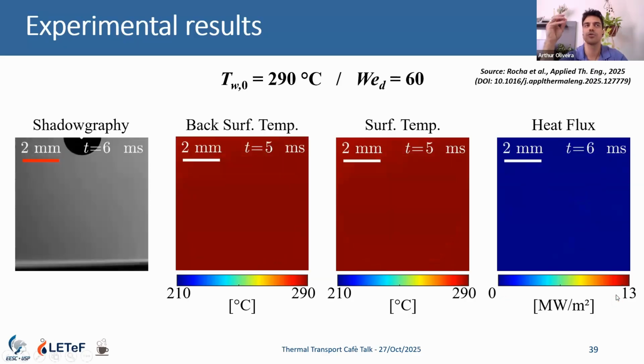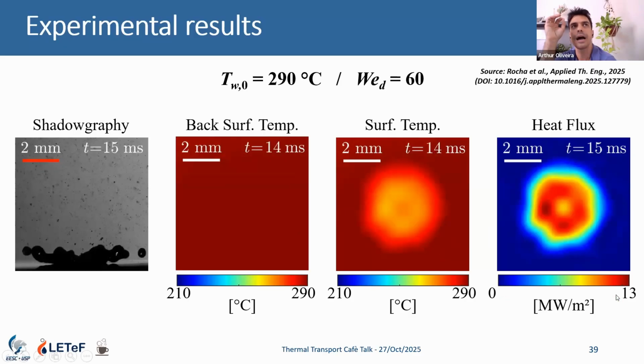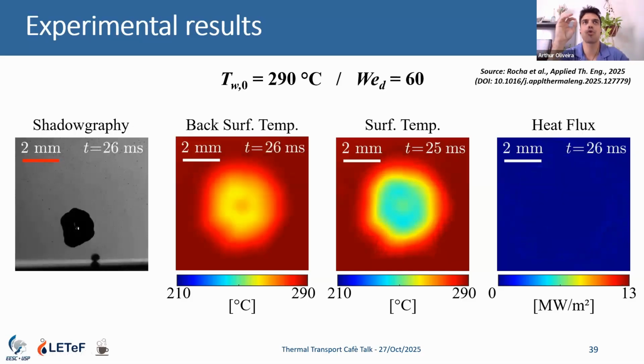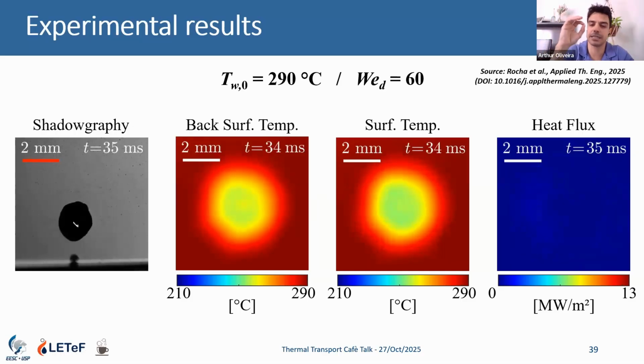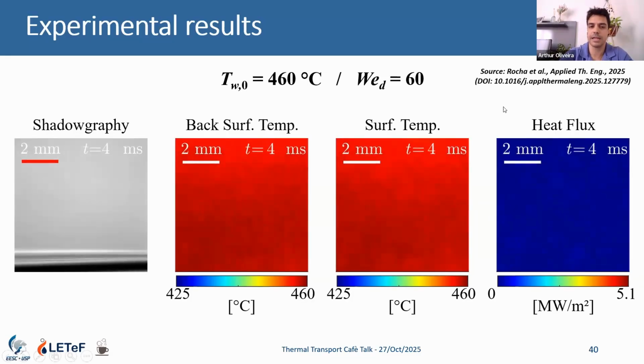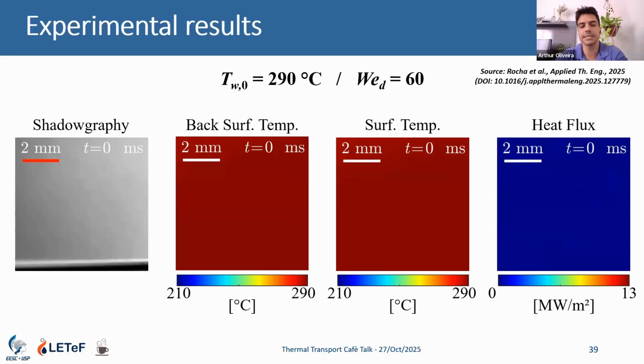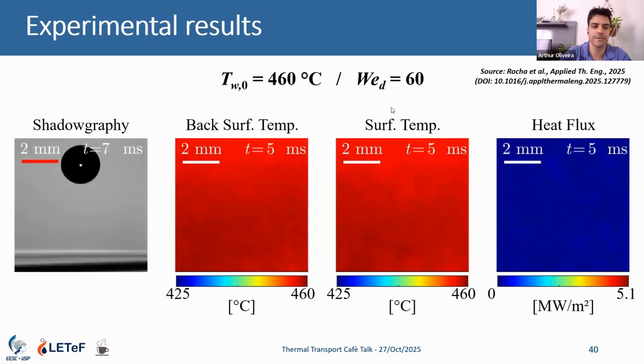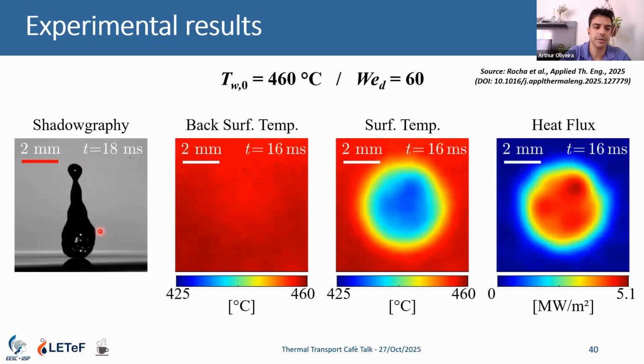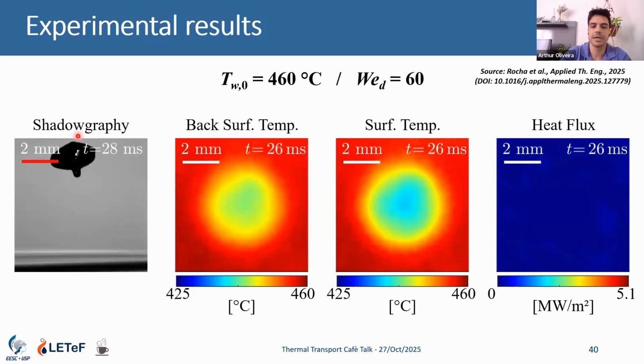As we have heat flux for the spray application, I'm interested in how much energy the droplet dissipates when impacting the surface. This is the result for 290 degrees, as I showed you here. And also for 460 degrees, a higher temperature, we can see the droplet rebound and now a different surface temperature, different heat flux profile here.